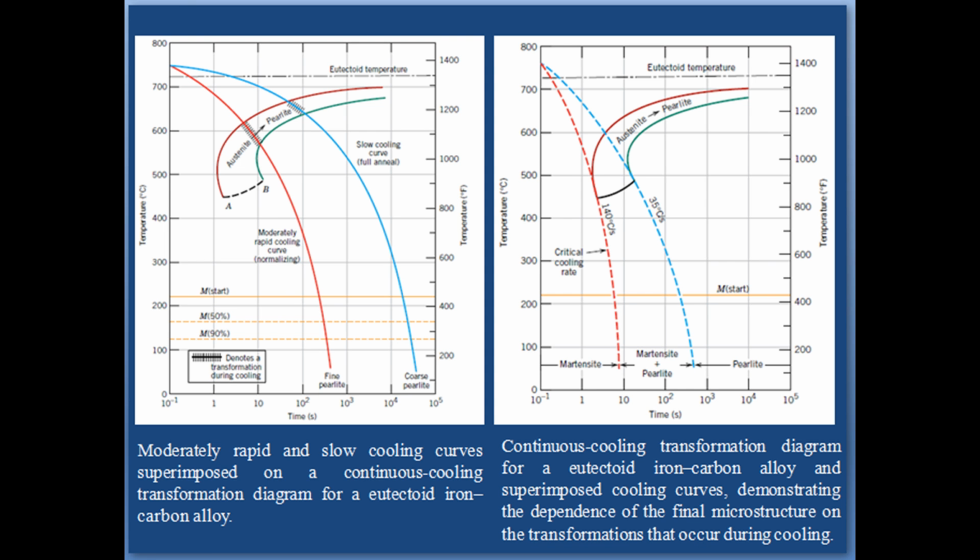Normally, bainite will not form when an alloy of eutectoid composition, or for that matter any plain carbon steel, is continuously cooled to room temperature. This is because all of the austenite has transformed into pearlite by the time the bainite transformation has become possible. Thus, the region representing the austenite-pearlite transformation terminates just below the nose, as indicated by the curve AB. For any cooling curve passing through AB in the figure, the transformation ceases at the point of intersection with continued cooling.